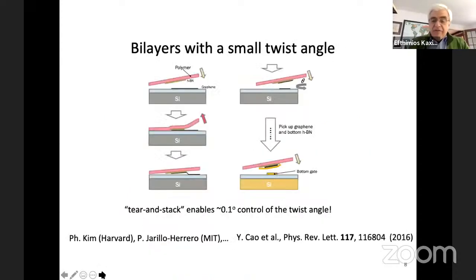So a few interesting developments very recently, in the last few years, have made the whole topic even more exciting. And here's what really led to this. It's the possibility to create a bilayer, but with a relative twist. The two layers are not exactly aligned one on top of the other, but they have a relative twist. And you can control this twist angle very, very accurately, which is quite amazing. So this is how they do it.